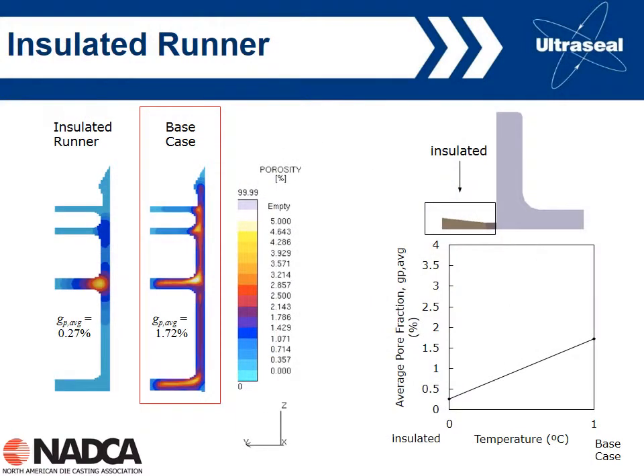And that's shown a little bit here, in the extreme. If we just insulated the gate, i.e. we had no heat extraction at all from the gate, we get a better case where we can reduce the pore fraction. But even so, even with the insulated runner, we're not totally eliminating porosity. We're going to get porosity in some of these heavy areas.